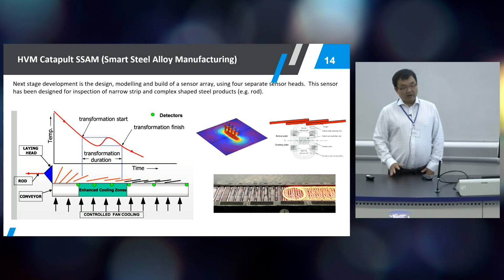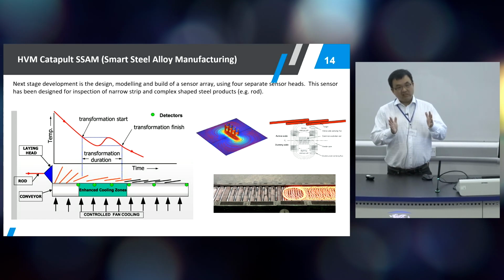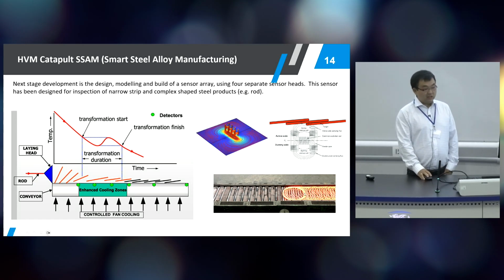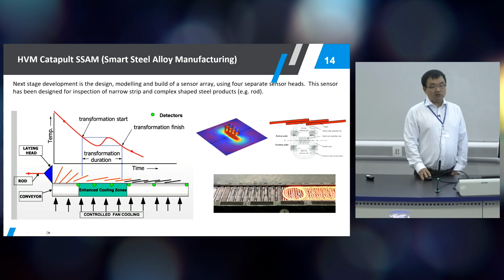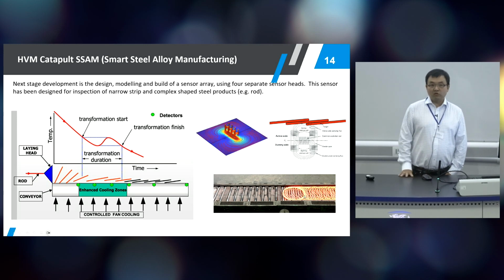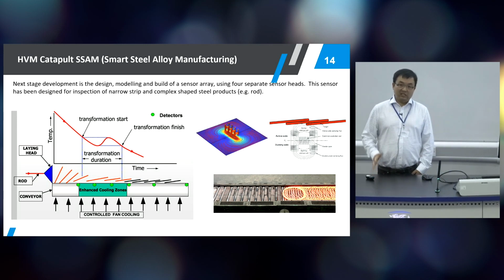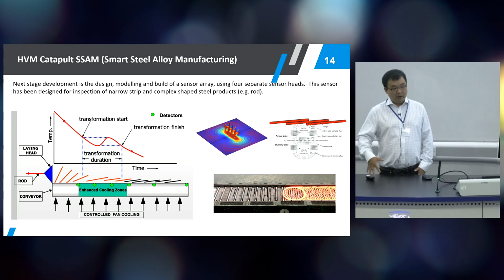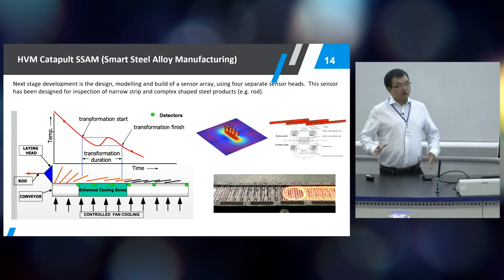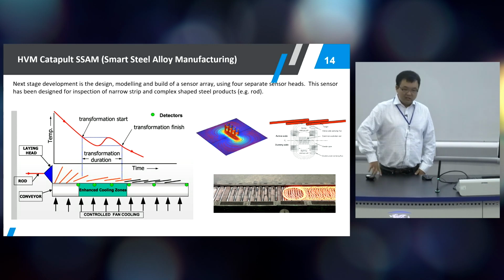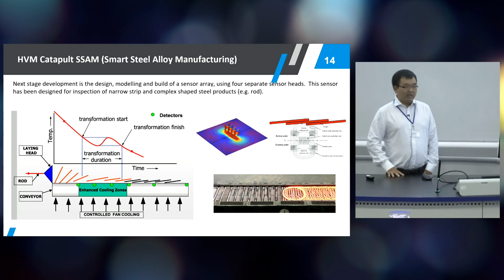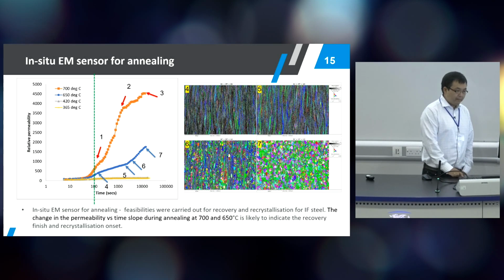The other benefit of having a few sensor heads across the width in this situation is, as you can see, when the rod is coming out, the different density of the layout of the steel means that the cooling rate could be different at the center or near the edge of the webs. So different sensor heads can potentially pick up when each different location starts to transform, because you want to control the cooling rate so that the transformation is uniform in a rod application as well.